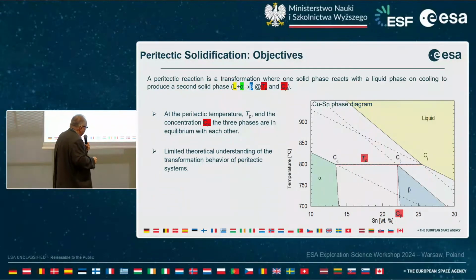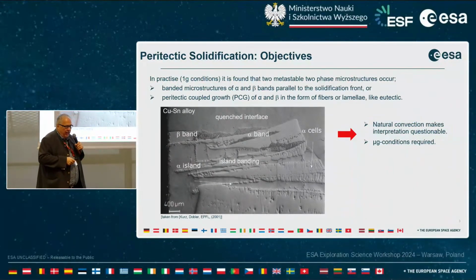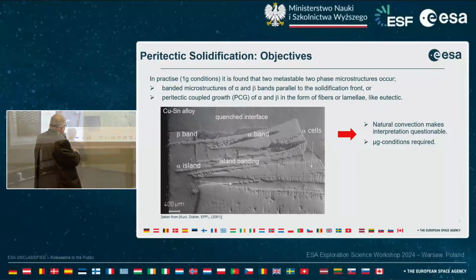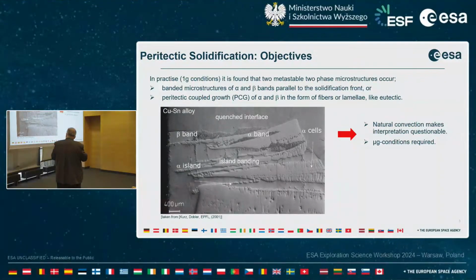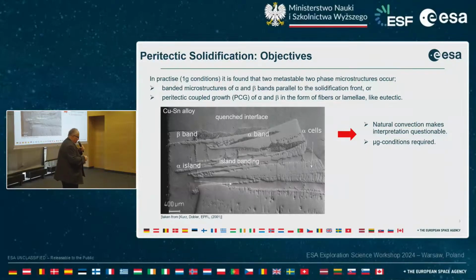Additionally, what's happened with inclusions in the liquid? Here you can see the quenched metal, and here you can see different things: here we have the initial alpha phase, and here a band of the peritectic phase, and how this occurs. This was one of the questions of this METCOM project, and since this is influenced by thermosolutal convection, microgravity experiments are required.